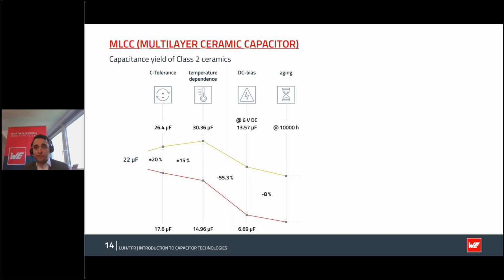So after all these effects combined, out of the 22 microfarads you used to have, in the best case, you have about 12.5 microfarad, so close to half of the initial value. And in the worst case, you're down to 6.15 microfarad, which is pretty much 1/4 of the initial value. You can use them like this, but you do need to make sure that you actually calculate all these effects to have a good safety margin in there. Otherwise, you might end up having a capacitor with not enough capacitance after some time.